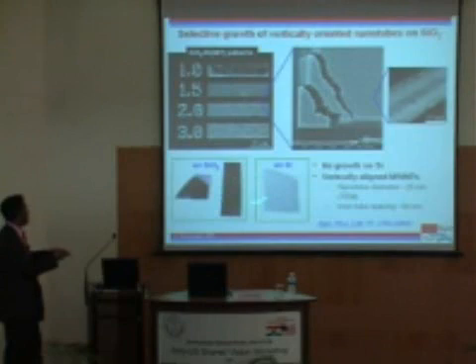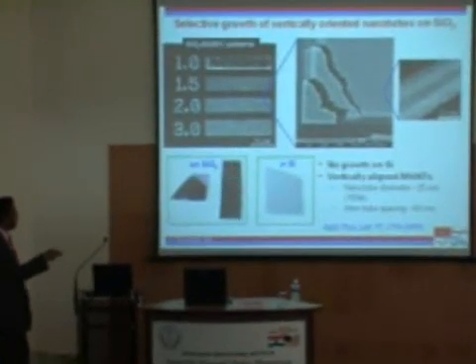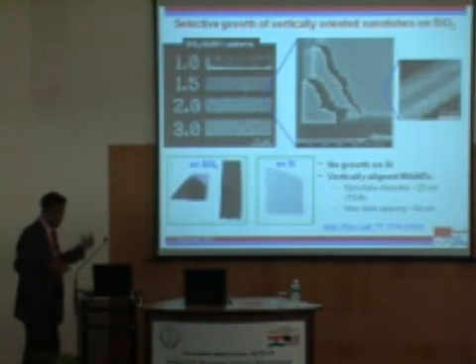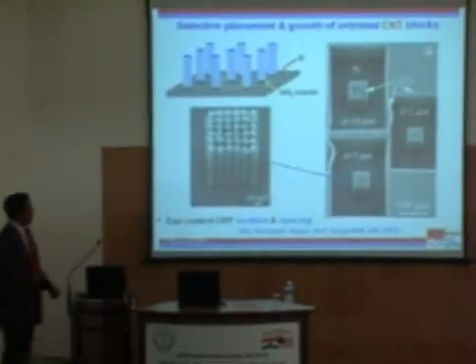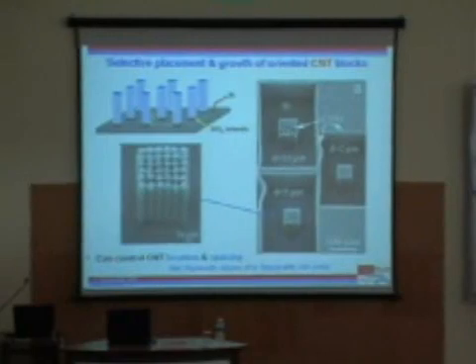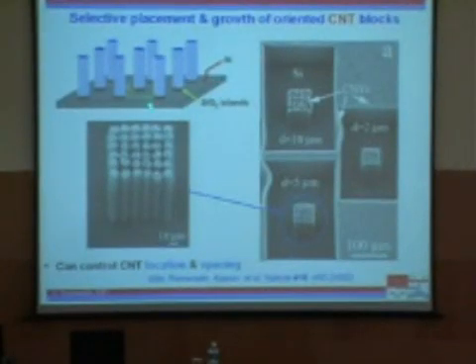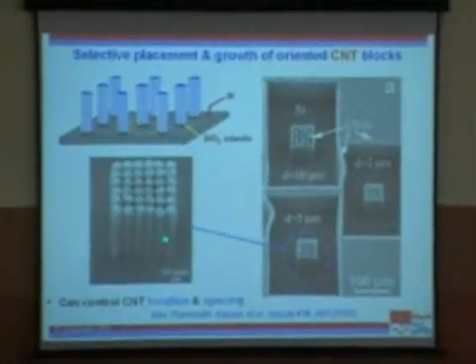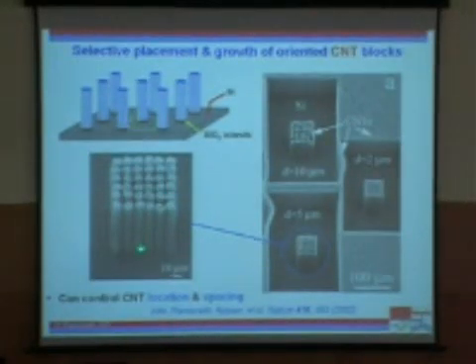If you put a piece of silicon into the CVD chamber, nothing happens. If you put a piece of silica, then it blackens. Using just these two features, I can use lithography to make discs of silica on silicon, and I would expect to get structures like this, and indeed I get these wonderful pillar-like structures, which actually consist of clusters of carbon nanotubes. So this is pretty good. That means we can assemble bundles of carbon nanotubes. Good first step. And these are all unidirectional structures.